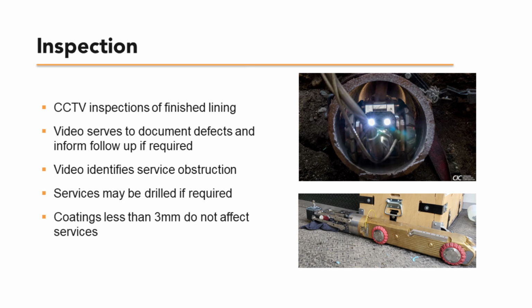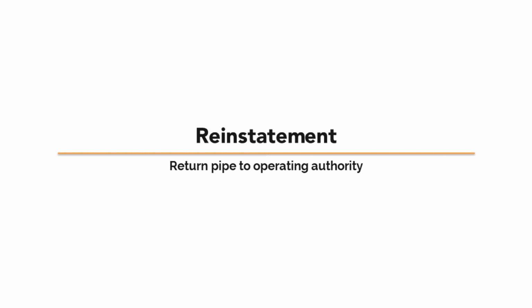In addition, corporation stops may be examined for obstruction. If blockage is excessive, the robot carries a drill which can be used to open up the surface connections. Testing has shown that coatings of 3 mm thickness and less do not normally require drilling. Cameras and cables are cleaned prior to use and wiped and sprayed with chlorine solution before entering the pipe.